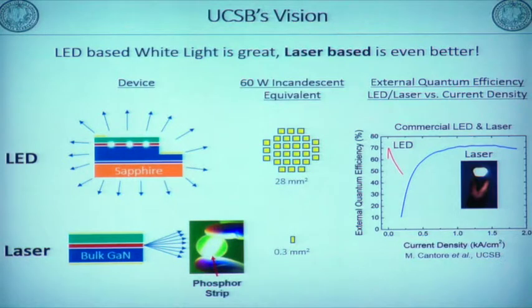But in the case of laser diode, you can see that with increased current density, the efficiency still gets higher, and keeps the highest efficiency up to a current density of more than 2 kiloamperes. So using laser diodes, we can make a very, very bright lighting source. You can also see the chip size. In the case of LED, we have to keep the current density less than 0.1, 0.2 kiloamperes per square centimeter. So to make bright light, we need a big chip emitting area, because we can't increase the current density. But with laser diodes, we can increase the current density dramatically, so using a tiny chip like this, we can make very bright lighting.